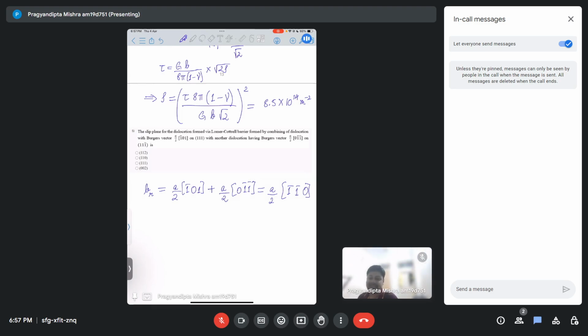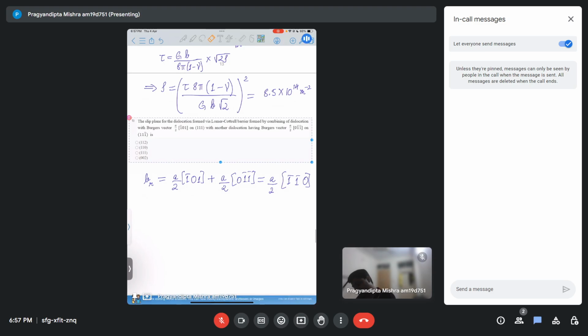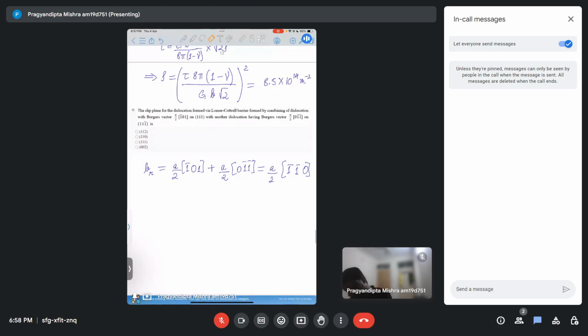That's the first step. Second step is, now we have to identify where they both will come and intersect. Now understand that these two dislocations lie on two different planes, right? So they can intersect only where both the planes are meeting. So if this is one plane, and this is my other plane, now where are they intersecting? They are intersecting at some line here, right? So there will be a line where these dislocations will intersect. So this line you have to identify.